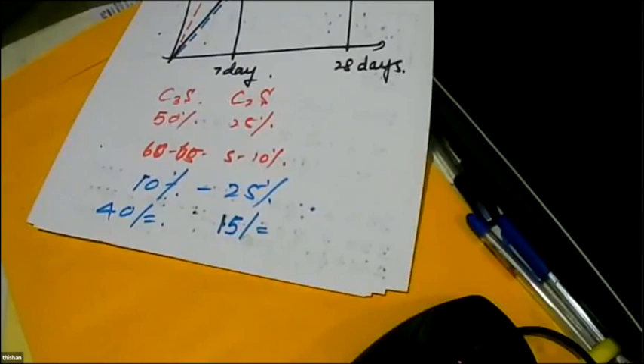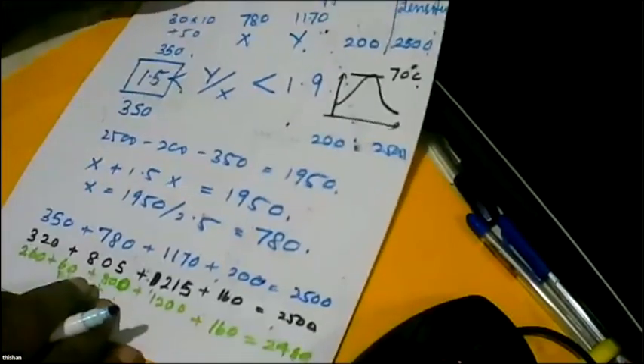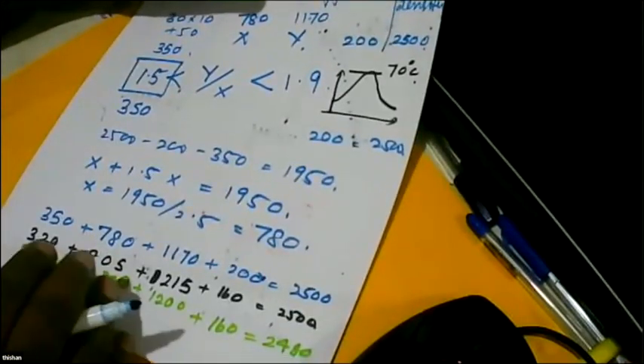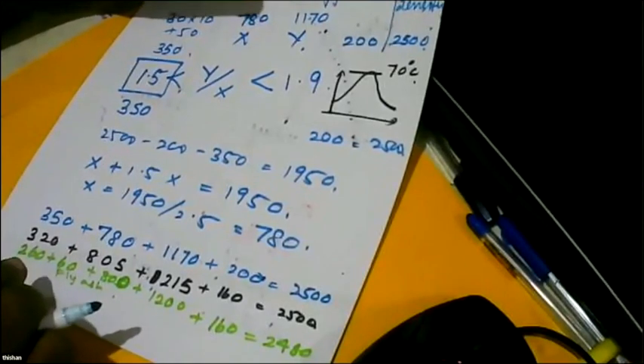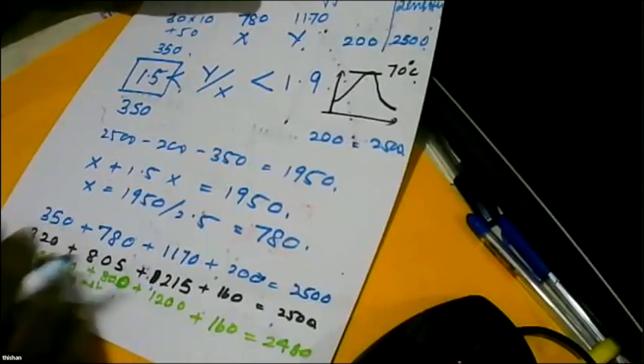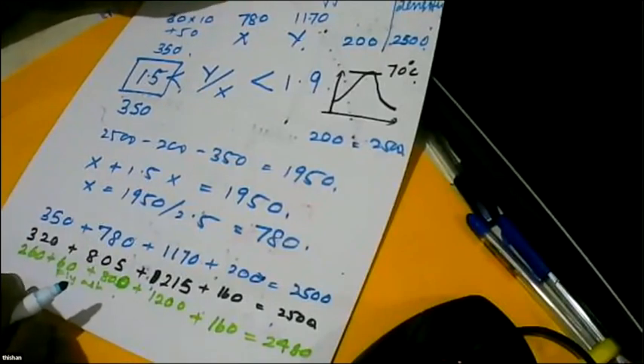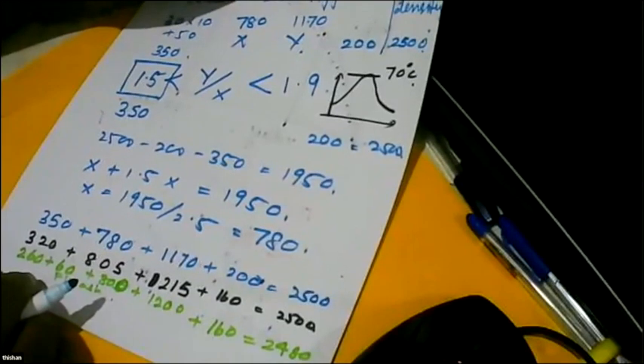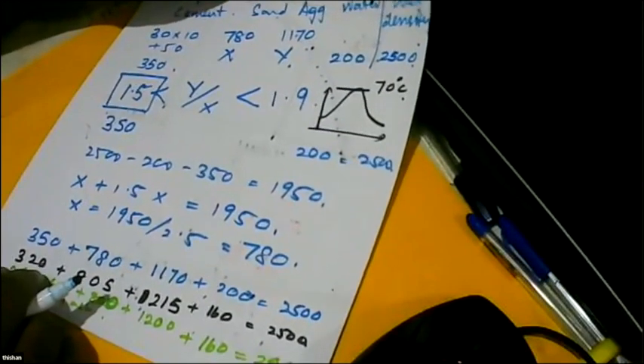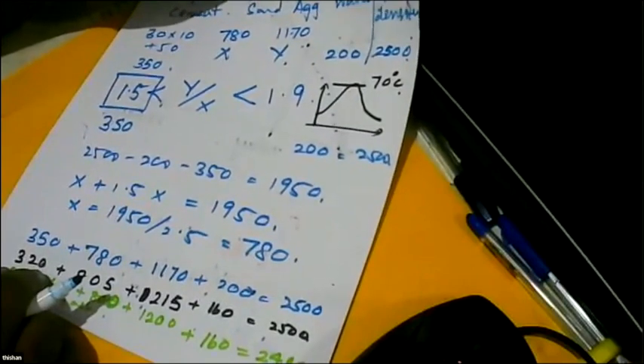You don't buy blended cements, you buy Portland cement and mix fly ash, then you can reduce the cost of concrete. On the other hand, if you are not concerned about the cost, you are concerned about the ease, how easily you can make concrete, you will buy a blended cement with 15% fly ash. Then automatically you are adding fly ash to the concrete and reducing the rate of reaction. And with a lesser rate of reaction, you have lesser chance of delayed ettringite formation.